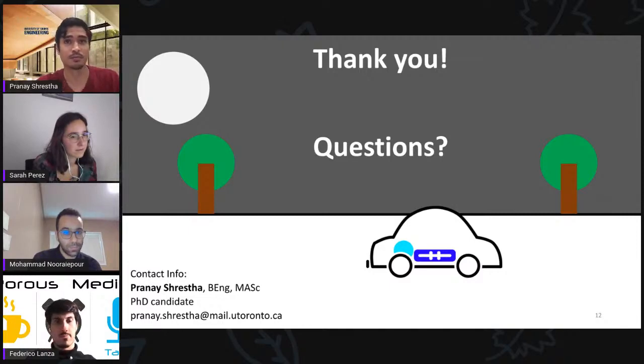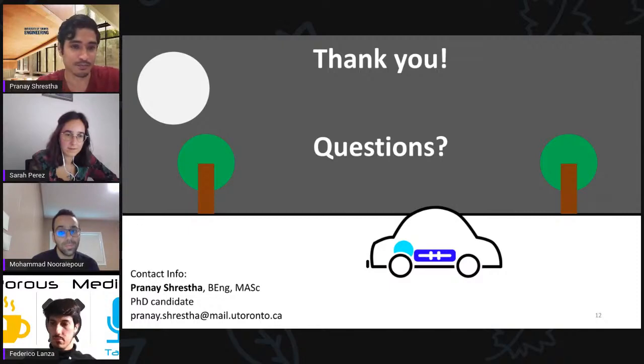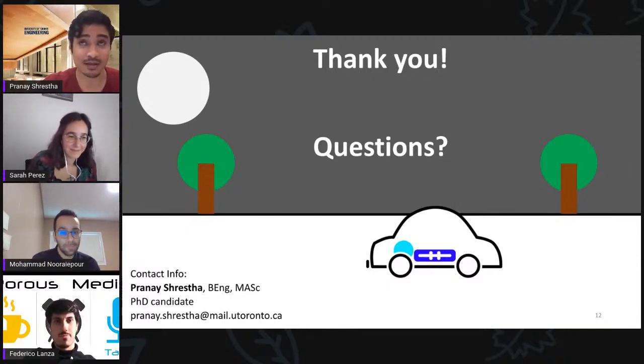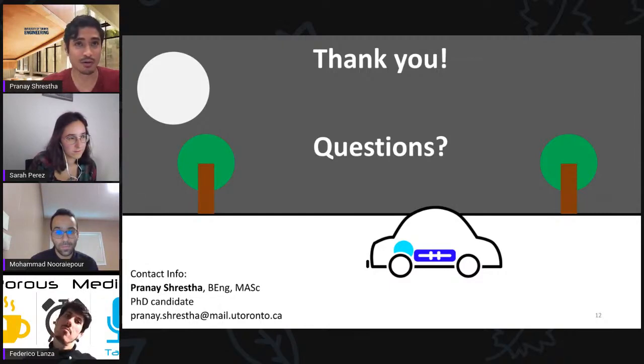It's a little bit different from confocal microscopy. Here, as long as the sample does not block too much of the X-rays, we resolve basically everything in the field of view at the voxel resolution that I stated, around 10 microns. There are X-ray sources or camera configurations that go even lower, to micron or even submicron resolution, and I guess that is interesting for the dynamics.